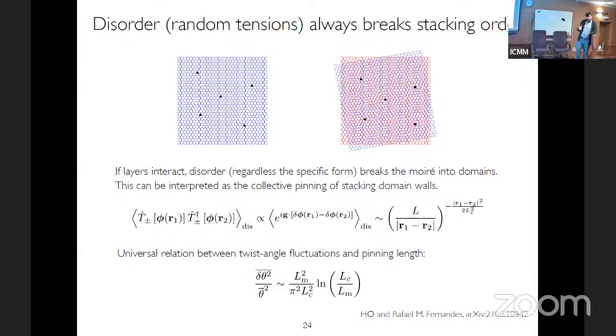So I'm going to consider now disorder in my graphene system, disorder that is going to be embedded in the lattice. What I mean by that is that, for example, in the figure on the left, these dark points are representing, for example, vacancies or atoms that are chemisorbed to the graphene layer or whatever. By embedded, I mean basically when I take my crystal and I move it to the other corner of the room, the energetics don't change. There is no energy cost associated with that. So that means that embedded disorder doesn't break long-range order in a crystalline lattice just because of this fact.